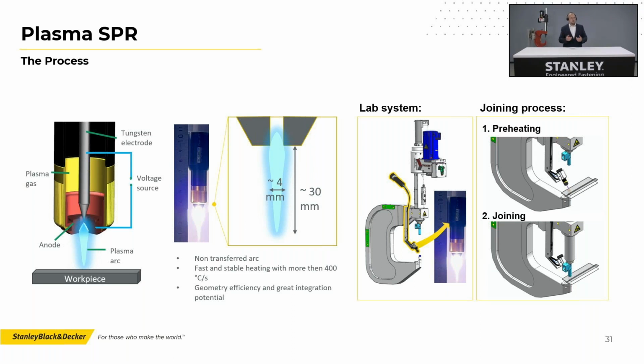We first used that in our stud welding systems to clean aluminum sheets, because they have dry lubricant and all of this. So we clean that to have better aluminum welding results on the stud welding side. And there we don't make anything soft. We just clean the surface. Then we thought about, okay, now we use that for plasma joining to pierce through 2000 megapascal with our plasma pin. Why not connect this to an SPR system as well?